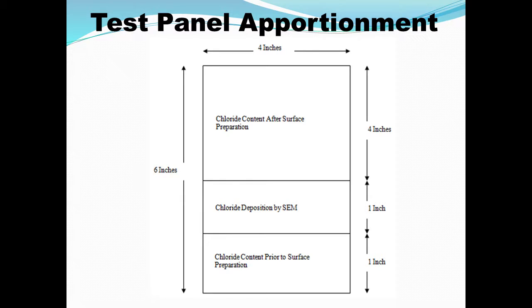Now, those 4x6 panels that we were looking at earlier, we randomly selected 3 panels for each surface preparation method. After this exposure to the salt fog and then cleaning by wire brush, a 1-inch strip of it was clipped off for evaluation of chloride contents. That's where I got that average of 500 micrograms per square centimeter, through boiling extraction of those pieces of steel.